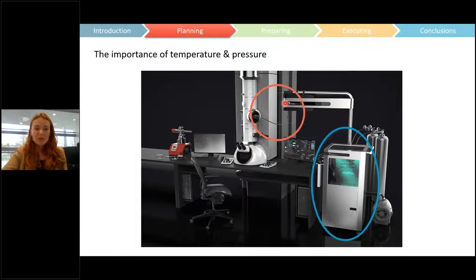The reason I mentioned before that we like to run all of our reactions at 1 bar or above, ideally ever so slightly above 1 bar, is because if we are below 1 bar, we leak water from the atmosphere into our lines, either where they connect to the actual holder, or in the manifold itself if it's not 100% leak tight. You'll leak water into those lines and you cannot get rid of that water. Working at overpressure means that even if you do have a minor leak somewhere, it doesn't matter because it's going to leak out.